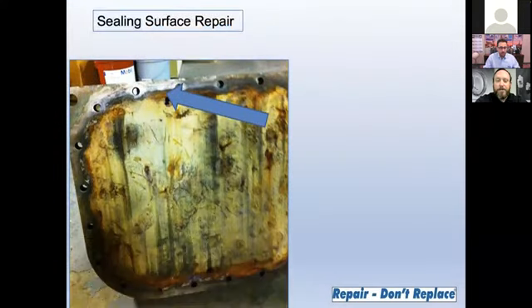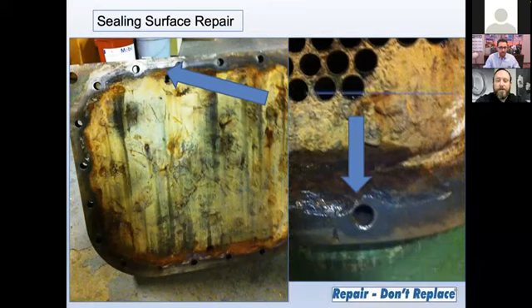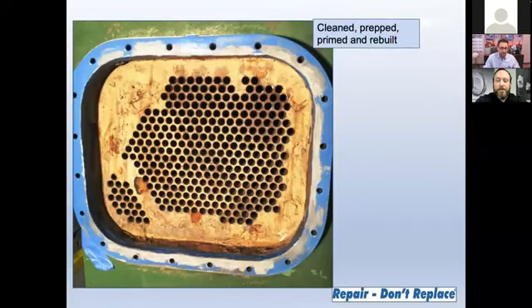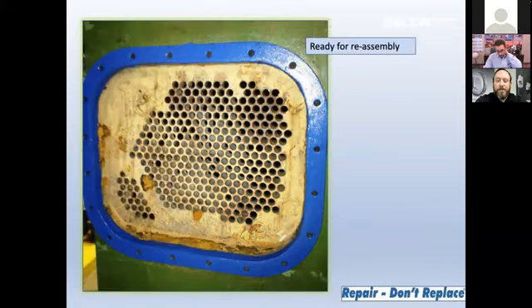Sealing surface repair is a lot of times the name of the game in getting our customers' equipment back up and running. Quite frankly, it's all about the seals, and sometimes it takes multiple steps to complete it. In this application, we originally completed the repair on the flange surfaces, but once we tried to get it all level, we actually had to go back over with a sander, get it flush again, and apply a final coat of the ceramaloid seal plus AC blue. We typically can do this in one day, again, and this was all done in one day and put back in service the next day.